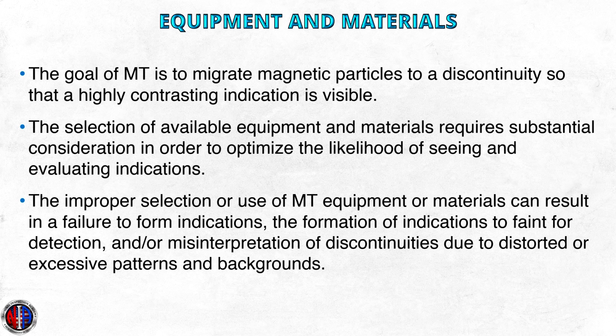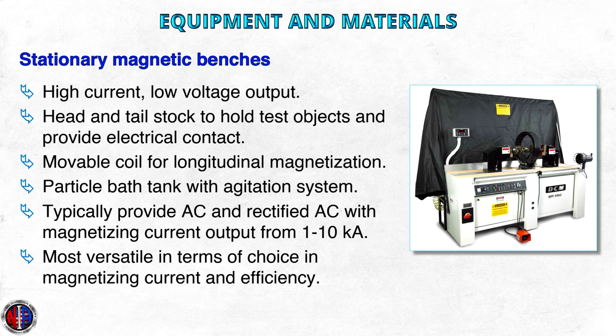Stationary magnetic benches. The wet method horizontal magnetic particle test systems typically feature a high current, low voltage output magnetizing source, a head and tail stock to hold the test object and provide electrical contact, a movable coil for longitudinal magnetization, and a particle suspension tank with an agitation system.